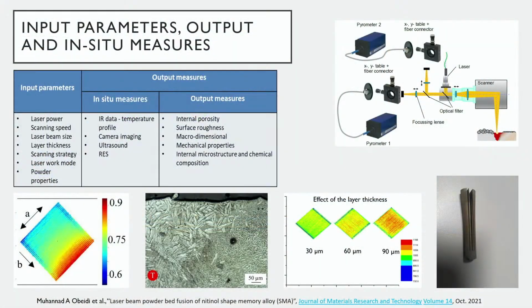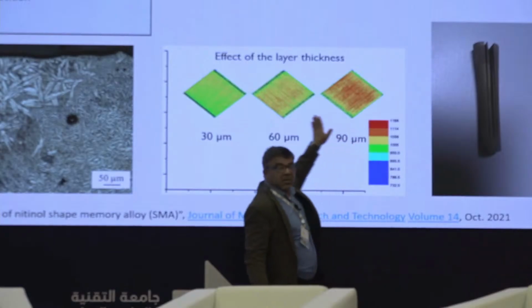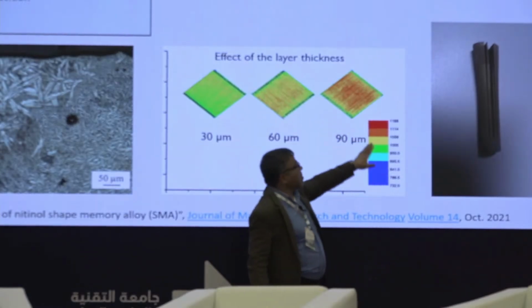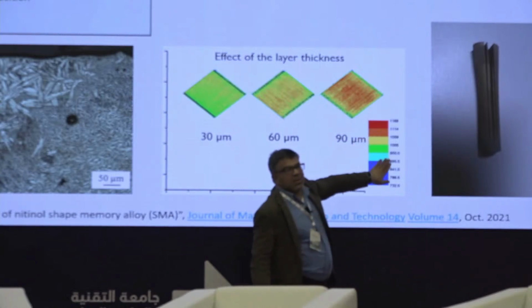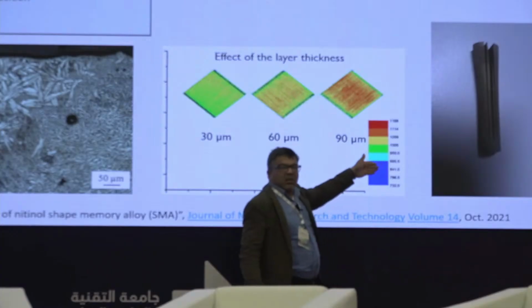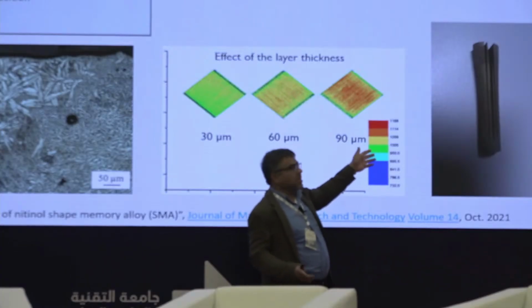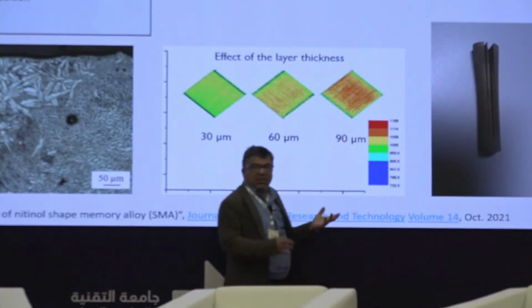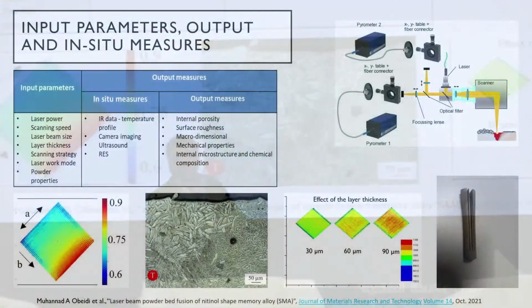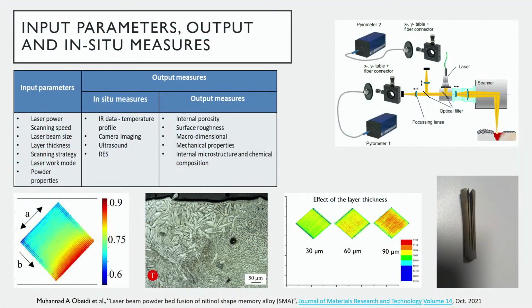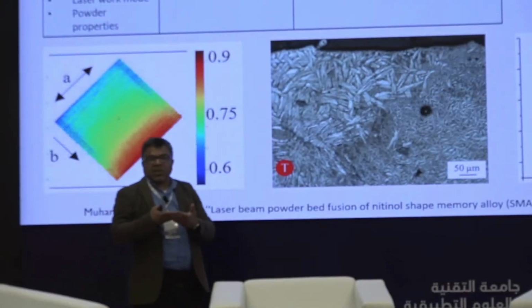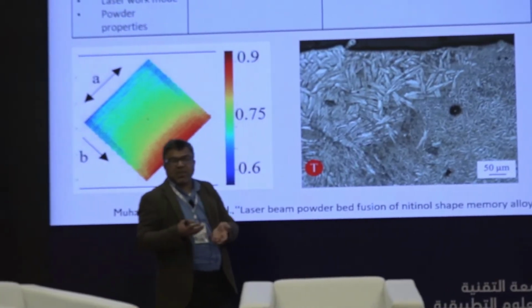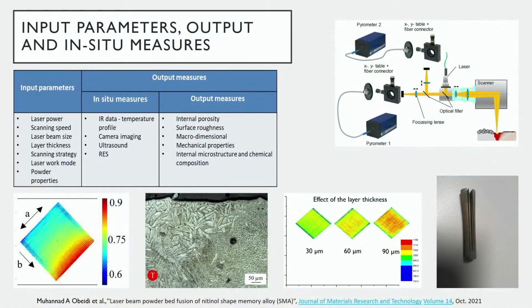Also, the layer thickness increases the temperature, even if you are using the same processing parameters. This is the 90 microns, higher temperature than this, based on this scale here. Please only use the colors to check, because this is not a temperature. This is a function of the temperature. We have thermal sensors that measure the temperature in millivolts. So these are millivolts. The reason why temperature is higher in higher layer thicknesses is that we put more powder already because the layer is thicker. And there are gaps between these particles. Gaps or gas gaps are like thermal insulators and so on. So these are the temperatures. I will show how we measure them.